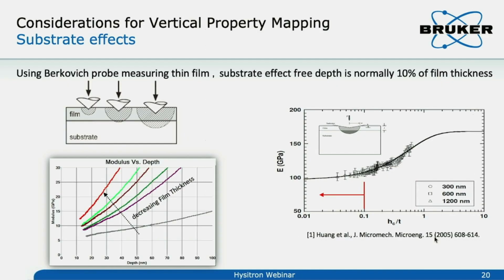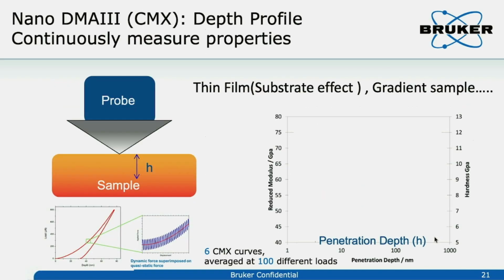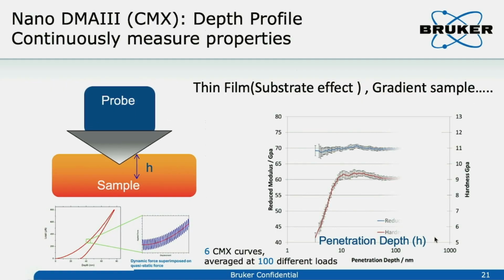So for the thin film sample, the challenge is the film thickness. We have a function we call CMX. This is continuous measurement, where X means hardness, modulus, whatever. So we can continuously measure the stiffness. We can continuously measure the hardness. We can continuously measure the modulus as well. So this allows you to do the indentation like a drill machine here.